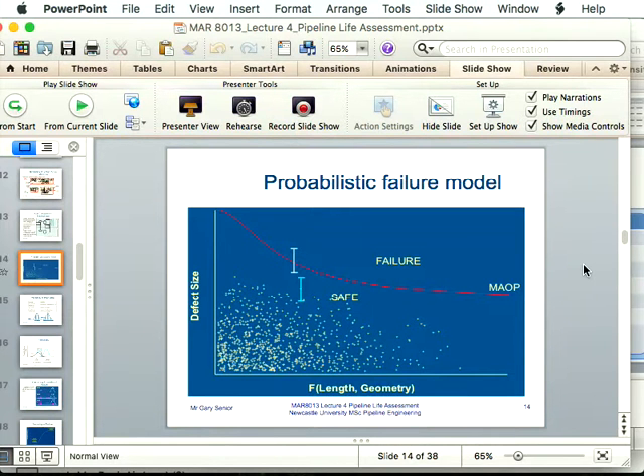Okay, so the probabilistic analysis would do multiple analyses of single features and identify how much significance it is on the defect changing size, and does it importantly cross that red line or not. Because if the significance of a given defect size, its tolerance, changes from here to here, for example, that goes into the so what category. It doesn't matter, it's very safe anyway. The issue is if you have a single defect measurement near to this line, but then if you apply the tolerance error on the reading and it takes it over the red line, you then need to repair it. So that's what the probabilistic analysis will do. It'll determine how many defects would cross over that line that you may need to repair. So it looks at variables of all the inputs in the calculation from a probability point of view rather than a deterministic one.